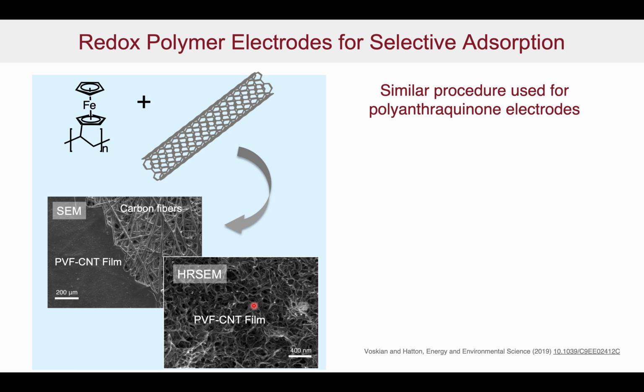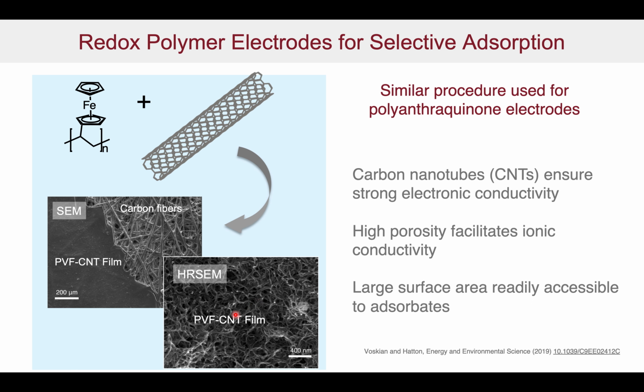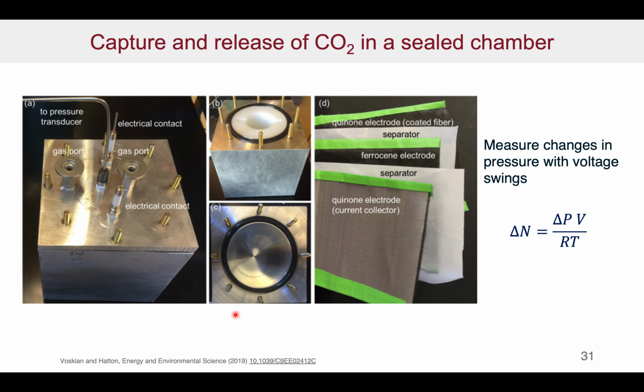Carbon nanotubes are really neat because they provide strong electronic conductivity. They provide a high porosity to facilitate ionic conductivity. And there's a large surface area that's really accessible for the adsorbates to find places to go. This gives an indication of the way in which we did the initial experiments, and of the electrode structure and how we assembled the electrodes.